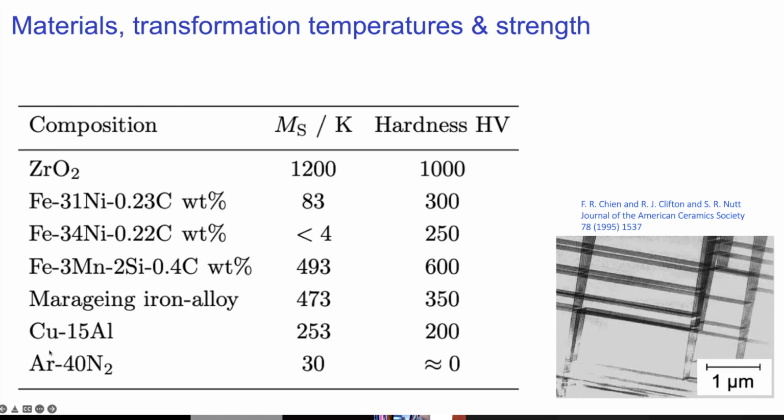This is a typical steel which will have a high transformation temperature. Sometimes when you have a high transformation temperature in steels, it may be the case that the martensite tempers at the same time as it forms. So you end up with a microstructure in which you will have some evidence of tempering, for example, the precipitation of transition carbides.